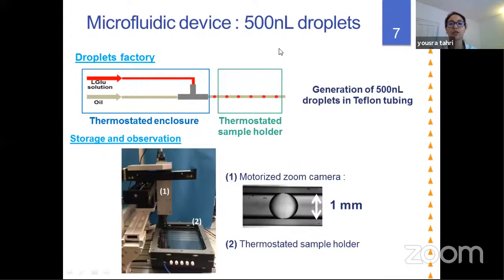Then we continued our investigation of the L-glutamic acid crystallization at another scale, in 500 nanoliter droplets in a microfluidic device. We generated the droplets in Teflon tubing by alternating the L-glutamic acid solution with oil. We stored our droplets in a thermostated sample holder, and this thermostated sample holder could be observed using a motorized camera. So we could follow the crystallization inside of the droplets over time.